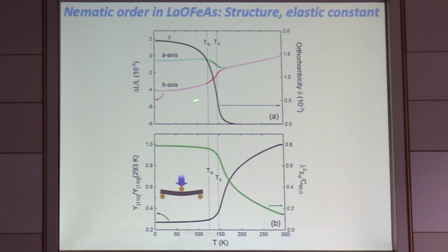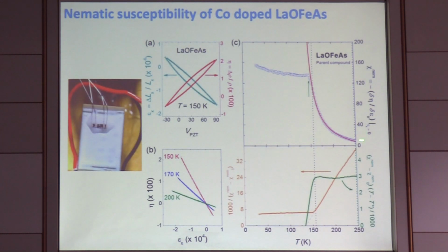So this is a structural phase transition, the orthorhombic transition, then the tetragonal phase, measured by capacitance dilatometry. You also measure the lattice softening, again very similar. So the structural phase transition is really very similar to what we know from the other systems. Also, the elastoresistivity shows a very typical behavior. We see the divergence here, telling us again about this component of the electronic instability which is driving the system. You can fit this with Curie-Weiss laws. You get a Curie-Weiss temperature which is slightly smaller than the actual transition temperature, but this is all more or less standard.